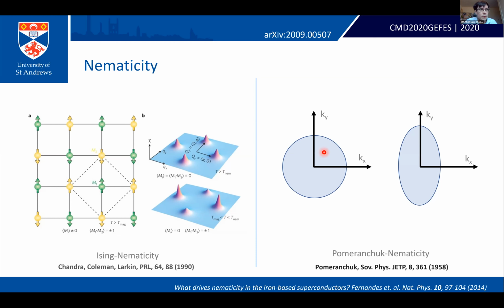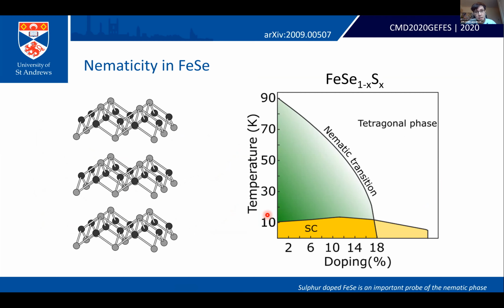But the issue is, in real systems that exhibit a nematic state, such as many iron-based superconductors, there's relatively little consensus on what is driving the nematic mechanism in these materials. And this is one of the reasons why so much attention has been placed on the material known as iron selenide, and more specifically, over the last couple of years, the iron selenium sulfur phase diagram. This here is the doping phase diagram as a function of sulfur doping and temperature. And you can see this phase diagram exhibits a large region of phase space with which to probe this nematic state and also its interplay with superconductivity.